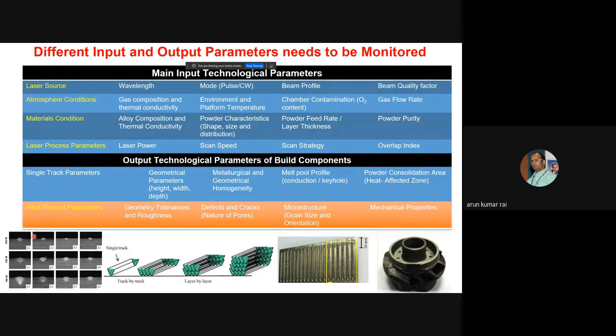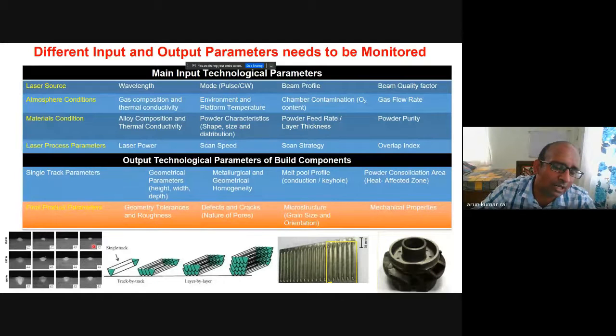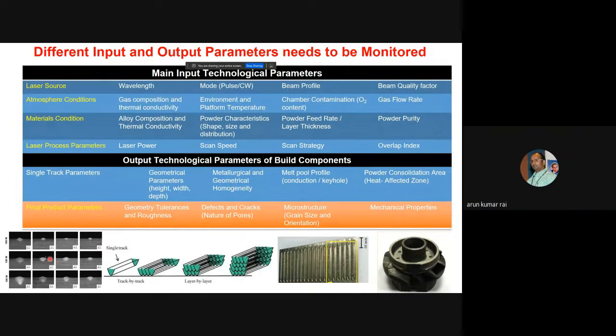And if you move along this, it is increasing the scan speed. But for a given power, when I am increasing scan speed, you can see the melt profile is reducing. It means I am not giving enough time to melt the material. So with optimization of your power and scan speed, you can get the desired melt profile, which can lead to a better product without any defect formation. So first we print a single layer and analyze it by microstructure and microscopy to see that there is no porosity formation. Then we do multi-layer deposition, and finally a product like this can be built.